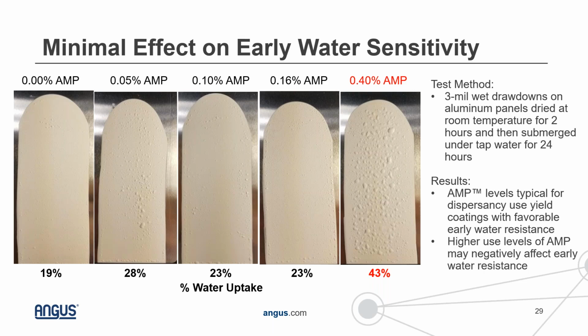Early water resistance is another critical test. And so we did check that with this formulation. So the test method was essentially a 3 mil wet drawdown on aluminum panels. And this was dried for precisely 2 hours at room temperature conditions. And then they're submerged under tap water. We also measured the weight of these panels before and after submersion to calculate a % water uptake. And so what we see in the images of these panels and also in the % water uptake is that there's not a huge change compared to the control formulation.